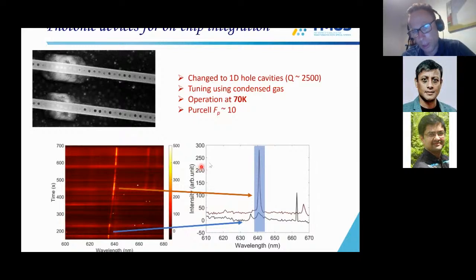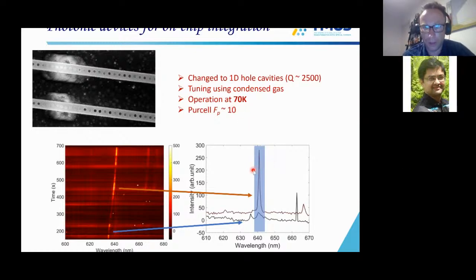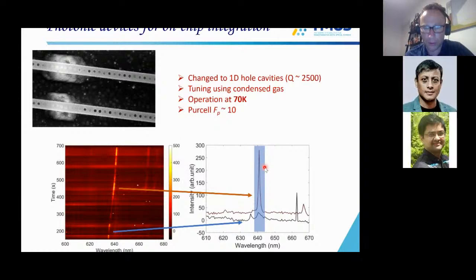Now, it's interesting here that you can do all these measurements at 70 Kelvin. You don't need to cool down to 4 Kelvin really, because the emitters are already narrow and the cavity modes are narrow. Unless you have a particular reason to go to 4 Kelvin, you don't really need to. Then you can do all the tuning experiments at 70 K and really measure Purcell enhancements and lifetime changes, etc. This is a great advantage over a standard quantum dot system, where you really need to cool down to about 4 Kelvin.